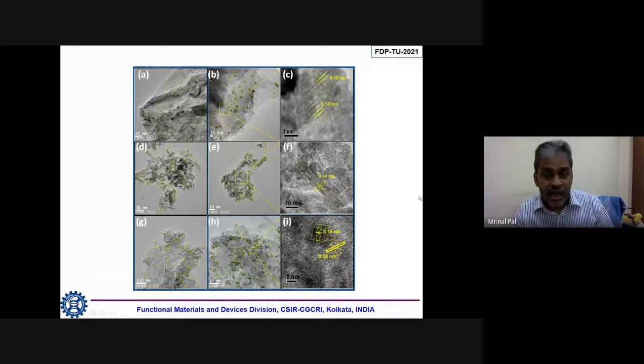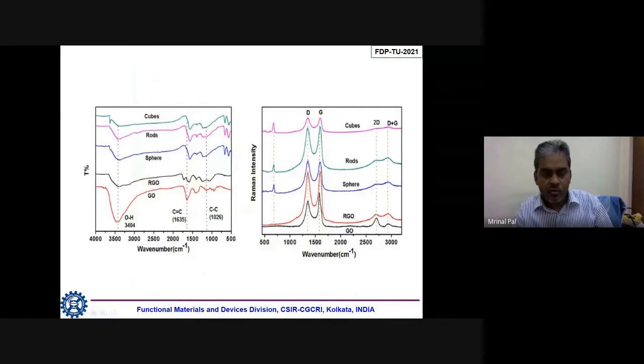The background is the same, but the cobalt nanoparticles are of different morphology, and because of that, we are able to create different functionalities. So the left hand side figure is the FTIR spectra, which shows the presence of C double bond and C single bond. And I must say that though we have prepared this cobalt cube, rod, sphere, RGO, GO, there is not that much change, or there is no peak shift in the case of FTIR, and also in the case of Raman. This right hand side figure is Raman. There is a change in intensity, of course, but there is no peak shift for this different morphology of cobalt nanoparticle.